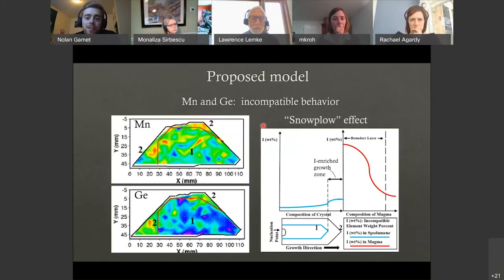So as the proposed model talked about in the beginning, the incompatible behavior or the snowplow effect, the manganese and germanium had this behavior. Because the high counts were in zone 1 and the low counts in zone 2, this is explained as the composition of the crystal changed. They were pushed along until they were finally forced to crystallize, or finally forced to become a part of the crystal.